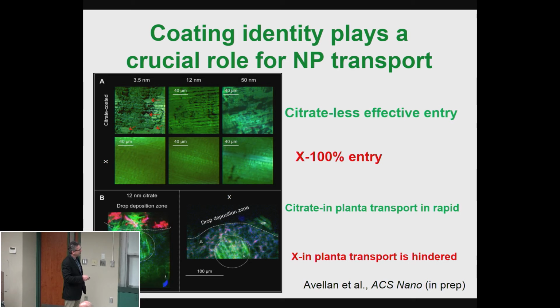This other coating that we put on gives us the chemistry to get through the cuticle of the leaf. We go back and you do not find any gold on that leaf. Maybe a little bit for the biggest particles, the 50 nanometer ones, but for 3.5 and 12, it's all gone. Now we take that leaf and we cut it, we make a cross section.